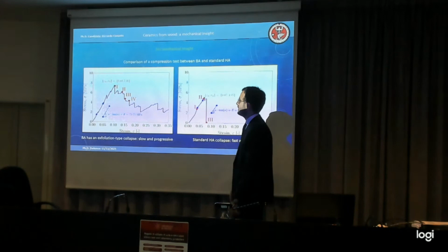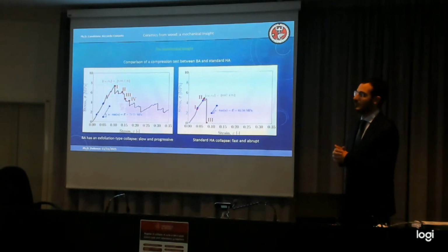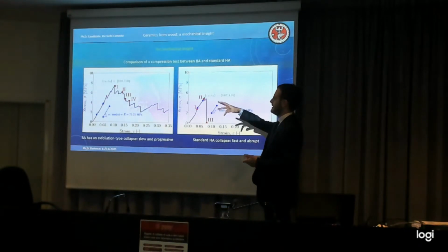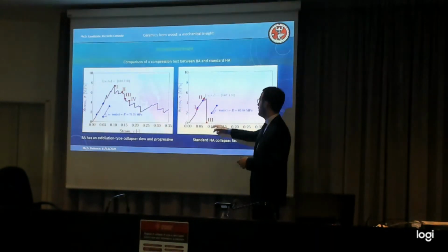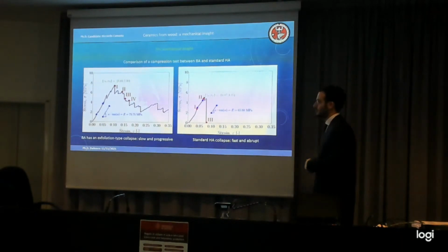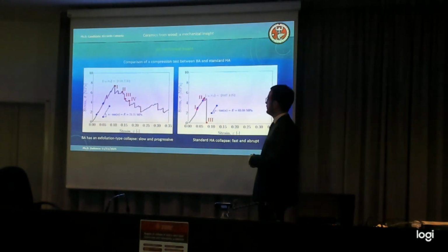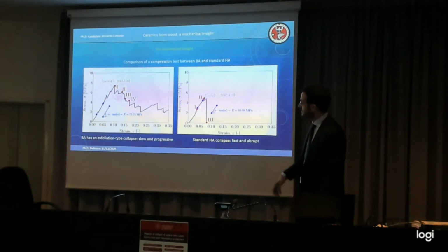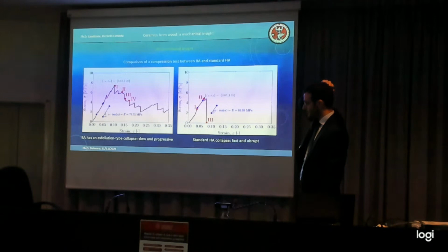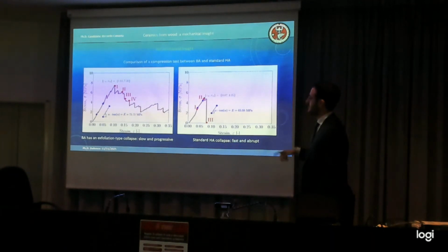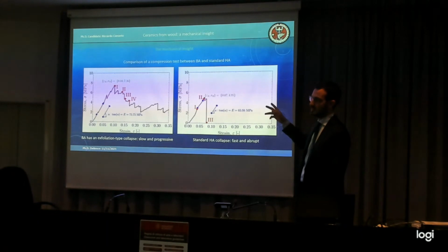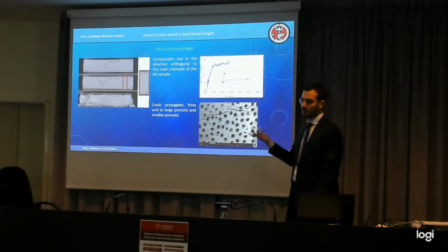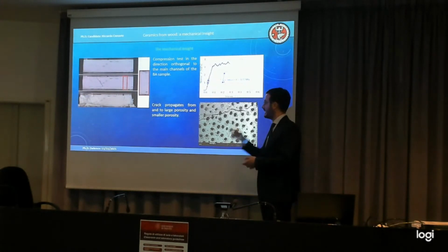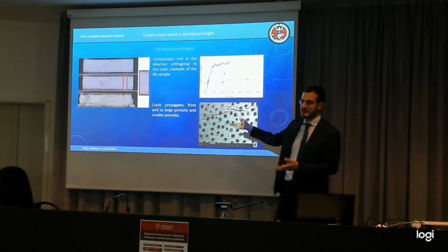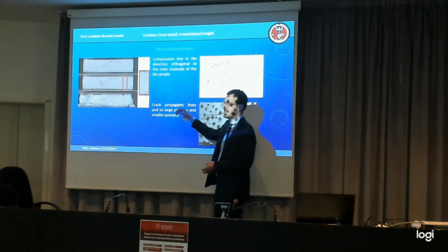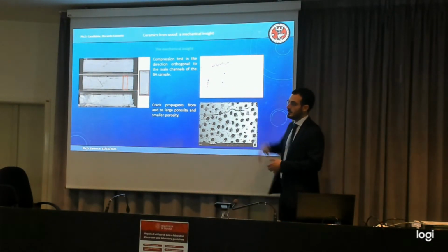And this is the compression test along the direction of the main channels. You can see that there is this nice behavior and slow fall, instead of normal hydroxyapatite, which is not suitable for bone replacement because you don't want something to crumble suddenly. Also, the overall mechanical properties, I mean, strength and stiffness, are superior, but this is in the direction of the channels, so this is something that is inherited from the rattan wood. Rattan wood is obviously at least transversely isotropic, and the obtained material is transversely isotropic. So the other direction behaves differently, but it's still better than the control.